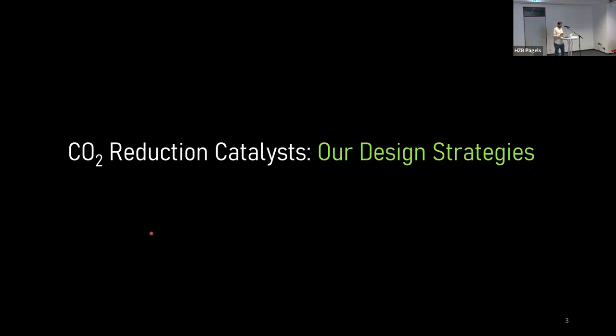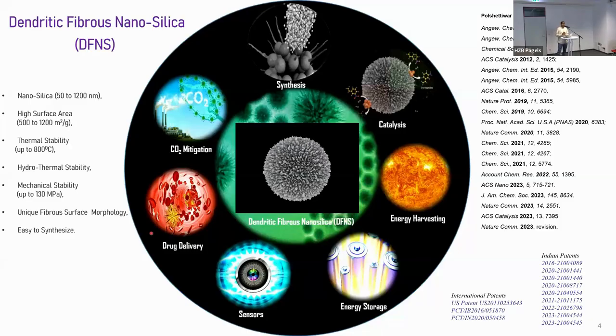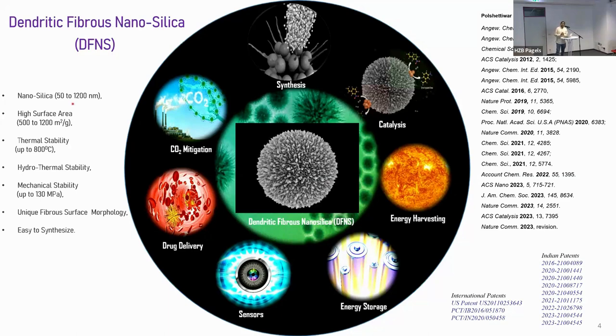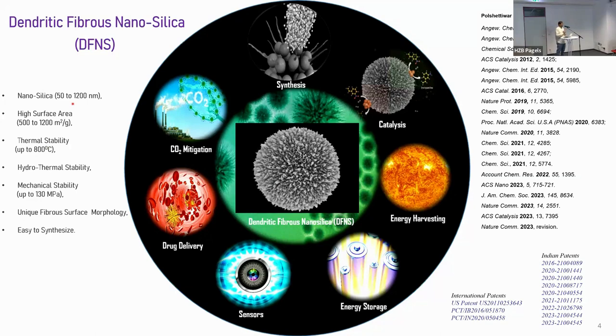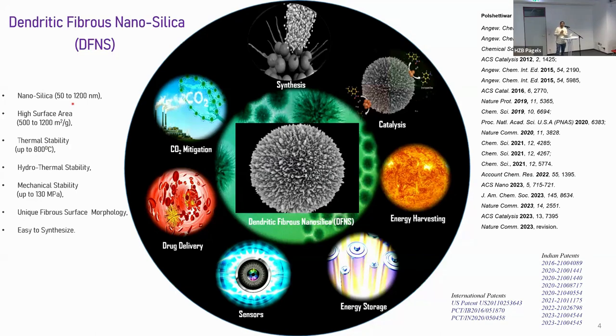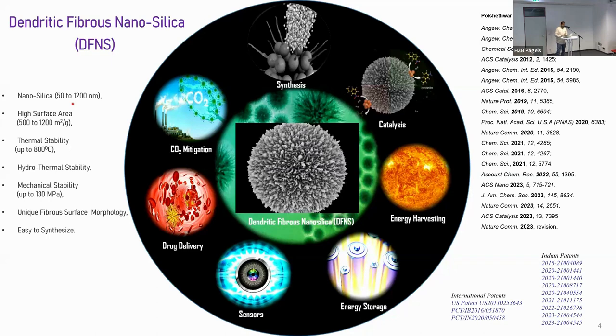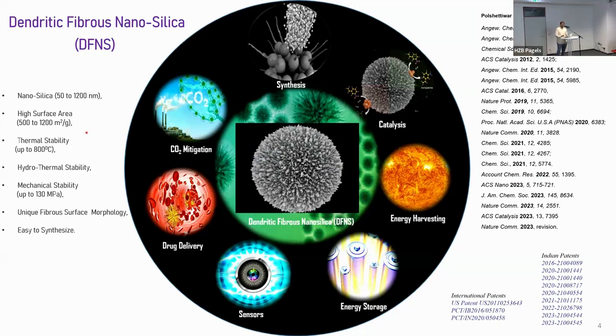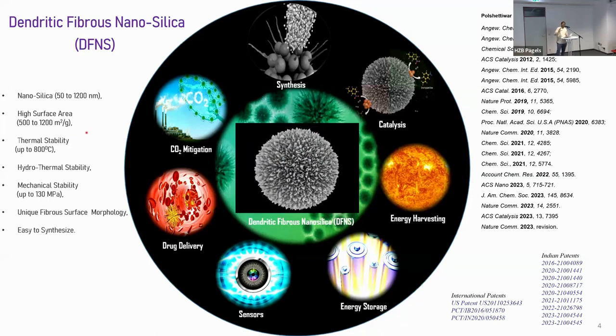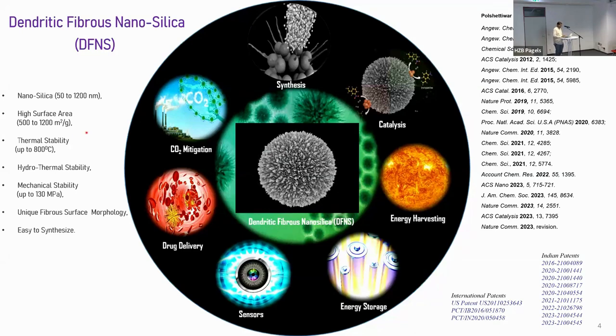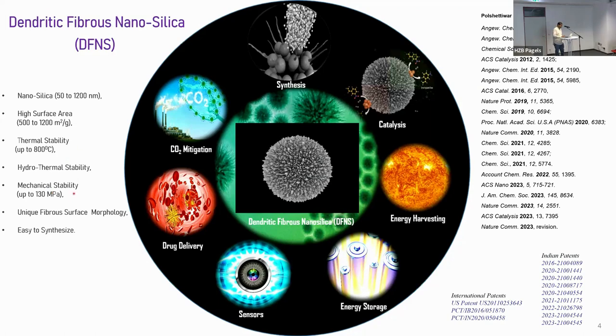So in our lab we have developed this new material called dendritic fibrous nanosilica. It's a silica with a nanoparticle size from 50 to 1200 nanometers. So you can make silica with 50 to 100, 100 to 200, 200 and so on, based on the requirement. There's a huge surface area, 500 to 1200 meters squared per gram. And in addition to the good textural properties, you can see it has excellent thermal and mechanical stability. That means I can use these materials for high temperature and high pressure reactions. And the uniqueness is the fibrous morphology.